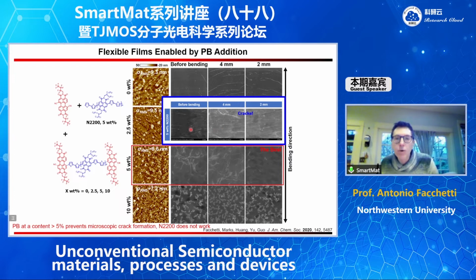And if we do a mixture with N2200, so the polymer without the red components, and you bend it and you add it at 5%, it's still cracking. So there is a huge difference between adding this polymer versus adding the polymer without the molecular recognition unit. So you need those.